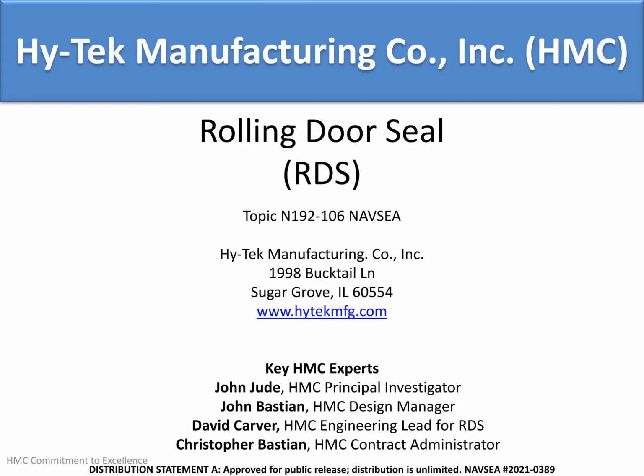During Phase 2 testing and evaluation, RDS prototypes were subjected to more than 20,000 simulated helicopter bay door opening and closing cycles without exhibiting significant wear or failure. When adopted for use on Navy's DDG destroyers, RDS technology will significantly extend the mean time before helicopter bay door failure, and therein significantly reduce DDG helicopter bay door seal replacement burdens and costs.